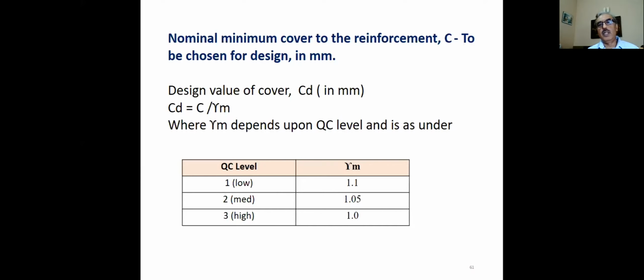Nominal - then we come to the minimum cover. We have got a nominal cover, then we have design cover. We put some factor of safety, because if quality control is high we keep it 1, since we are not permitting any negative deviation in the cover in our specification tolerance factor. But where the quality control level is poor, the cover can come down, so we have some factor of safety on that also.